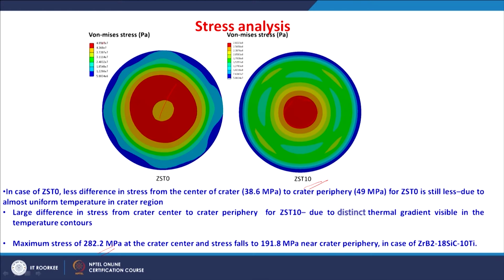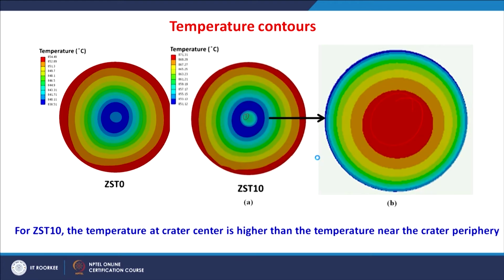So, a maximum stress of 282 MPa is found at the crater center, and this stress falls to 192 MPa nearer the crater periphery in case of this ZS T10. Such a difference in the stresses can be understood because of the temperature differences from the center of the crater to the periphery of the crater. So, for this ZS T10, the temperature at the center is higher than the temperature at the crater periphery. You can see this crater, this is the simulation for the temperature contours, the temperature contours for the crater region only.